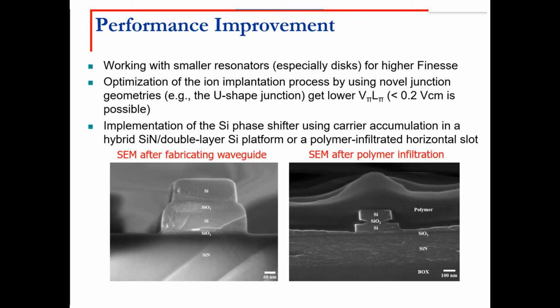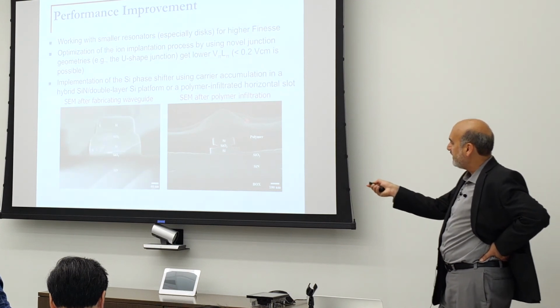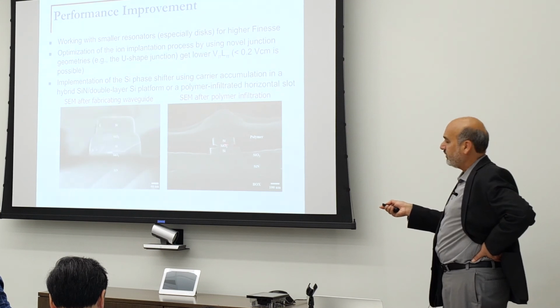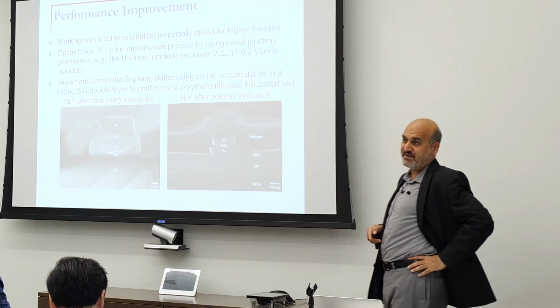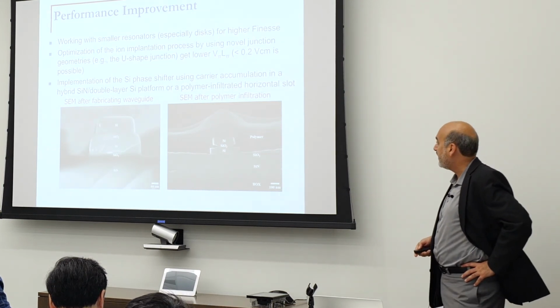We are also looking into etching the oxide underneath and infiltrating it with polymer. This is a crude example of a first trial. And then using polymers will allow us to apply a voltage and use the electro-optic effect in polymer, which is very fast and sensitive. So that opens up a lot of capabilities.